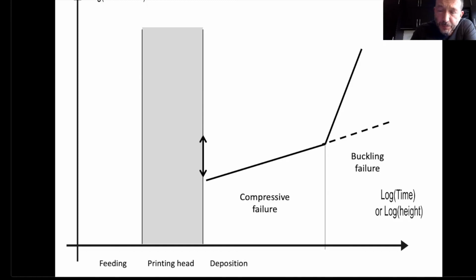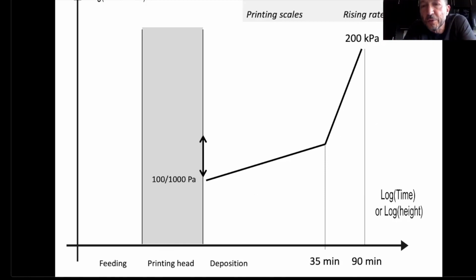So it means that when you print, you need a yield stress that is in an initial window for the filament or the layer to have a controlled shape. Then you need this yield stress to progressively increase with time or height so that it is able to support the weight of the layers above. But at a given critical height, you switch to a buckling failure regime that forces you to have very high values for the consistency of these materials.